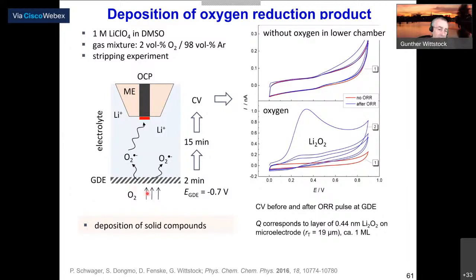Okay, if this is the case, we can provoke that experiment even more clearly, and that is done here. So we make oxygen reduction at the gas diffusion electrode, hold the microelectrode at open circuit potential, and passively collect the peroxide. After that, we make a stripping experiment, and you see here the result. We do the whole procedure, but have only argon in the cell, no oxygen in the lower gas compartment, and you see there is still a little bit of a trace, which is probably still traces of oxygen coming in.